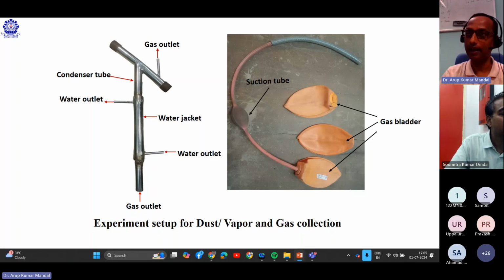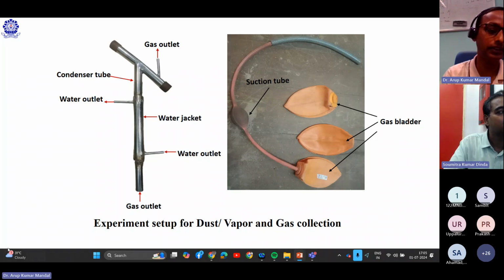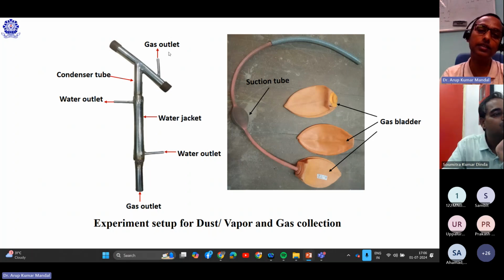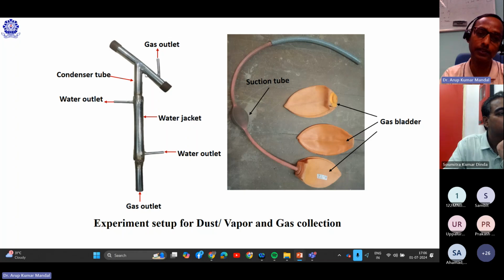So we got the metal hydrides, mainly iron hydride and manganese hydride. Silicon hydride we have not got, because at that temperature, when it goes to the upper portion, it reverts back to silica. Therefore we have got silica, but manganese hydride, iron hydride, and different types of complex hydrides we have observed. You can see my cursor here. When we open this water jacket area, major deposition of the metal hydrides is formed. From the area where the dust catcher is, for dust capturing, we got majorly solid particles. But the major hydrides are deposited here at the colder zone where the water circulation is done.